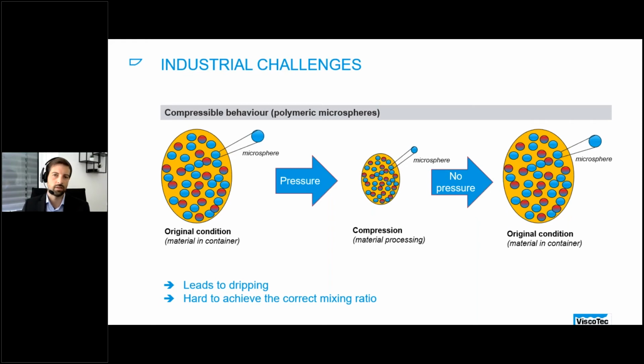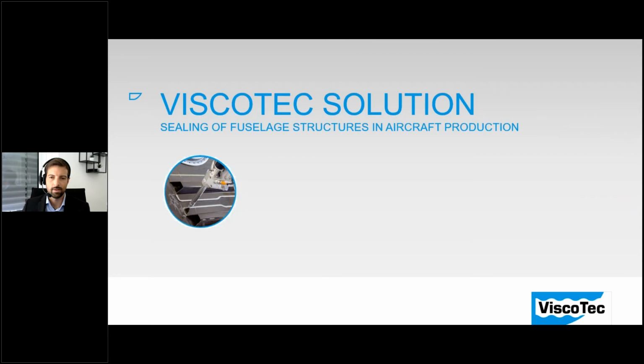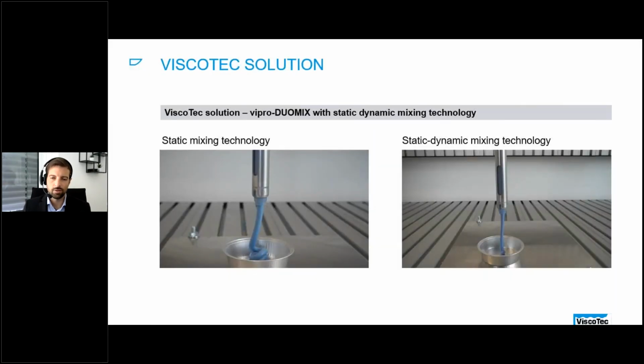So the overall volume is reduced, and once the material exits the outlet of the static mixer, for instance, and it is on the part itself, it starts to relax again, and the volume increases again to its original condition. And this leads definitely to dripping in cartridges, for instance, and it's hard to achieve the correct mixing ratio. Based on this industrial challenge, I would like to present you our Viscotec solution. So next slides, please. Before I introduce the dispensing system itself, I would like to put a focus on static mixing technology and static dynamic mixing technology.